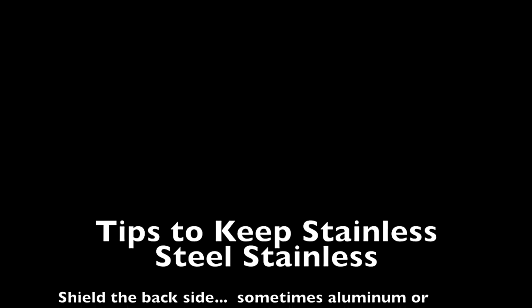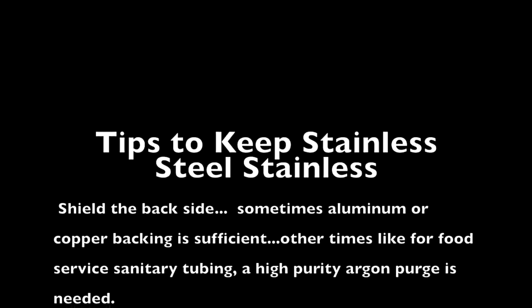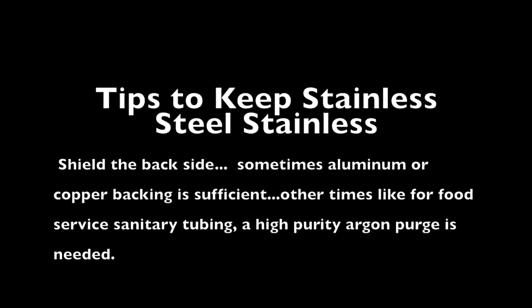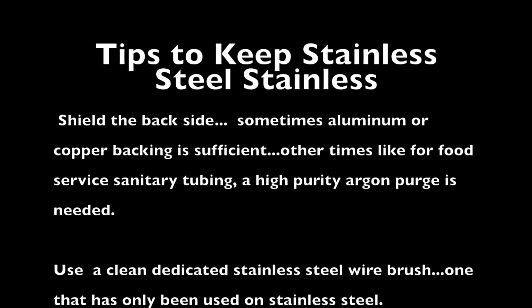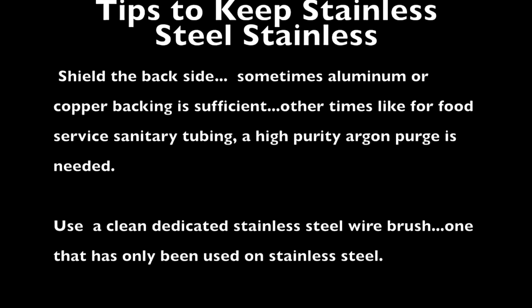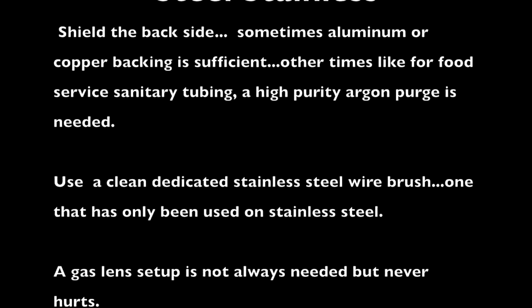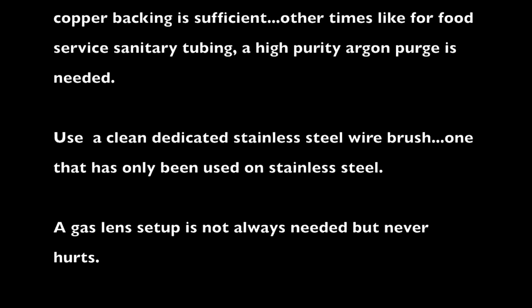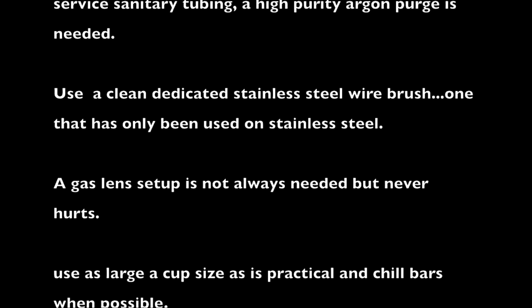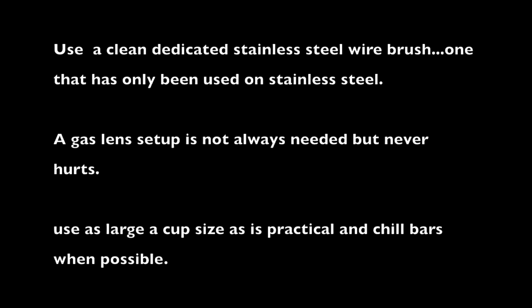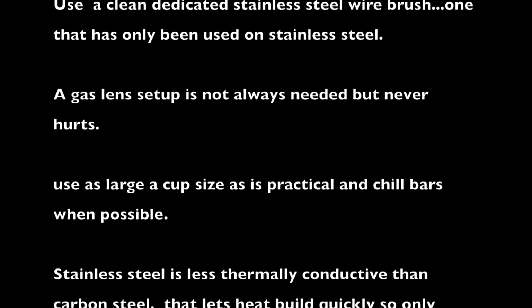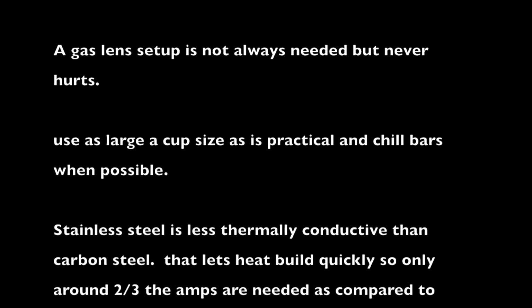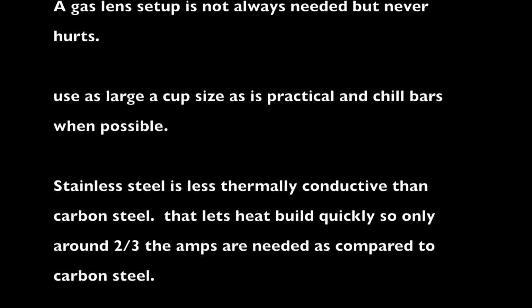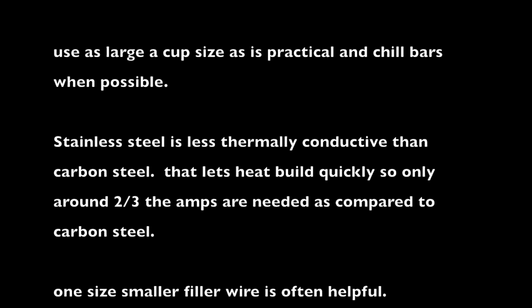All right, let's talk about some tips for keeping stainless steel stainless. Shield the back side. Now sometimes aluminum or copper backing is sufficient shielding. Other times, like for food grade sanitary tubing, a high purity argon purge is the way to go. Use a dedicated stainless steel wire brush. Dedicated means one that has only been used on stainless steel. A gas lens setup, not always needed, but never hurts. Use as large a cup size as is practical, along with chill bars whenever possible to pull that heat out. That helps with discoloration as well as distortion.